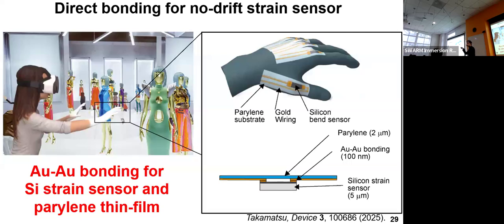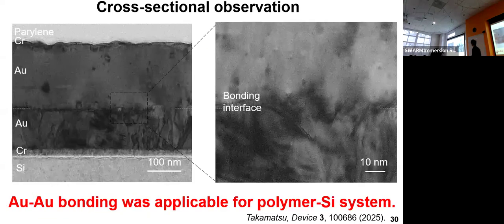So we added the evaporated gold onto the silicon strain sensor surfaces, and we applied the water vapor plasma to make the bonding of the silicon sensors and the parylene films. And we could achieve the perfect bonding of such different substrate interfaces. And then this is the TEM observation. There is almost no interface in the TEM images. The two regions are almost merged, fused, as shown here. So we could achieve this direct gold bonding system for different substrates.